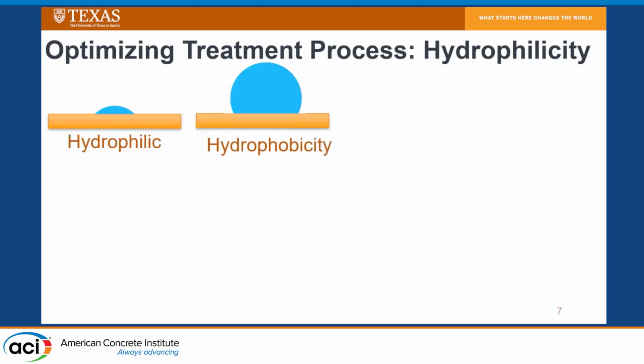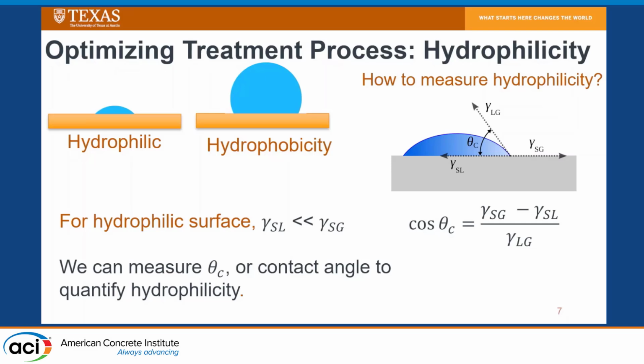So in order to characterize the hydrophobic or hydrophilic nature of our treated rubber, we looked at doing contact angle measurements. Essentially, the key thing that you need to know is that when your water likes your substrate better than the water likes the gas, in this case air, this is going to reduce this contact angle between your water and the substrate because your water is going to spread. So essentially what we want to do is to have an acute angle. We want to have angles less than 90 degrees because this is going to indicate that you have better wettability of the water on your rubber surface.